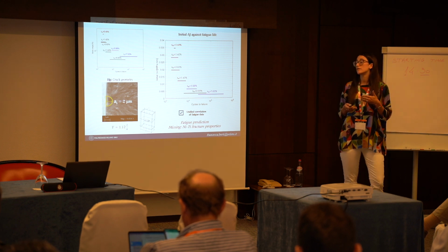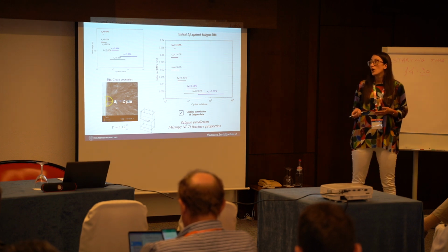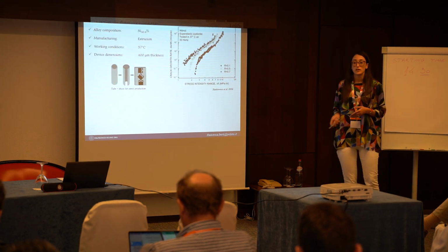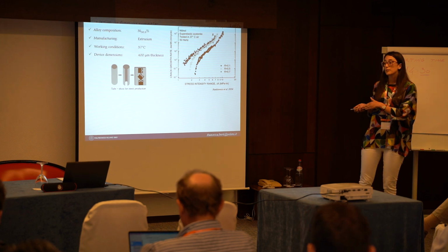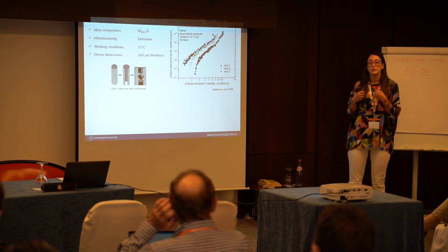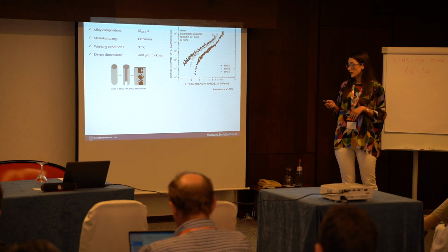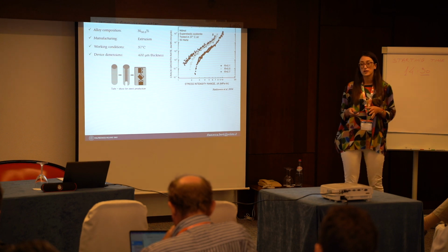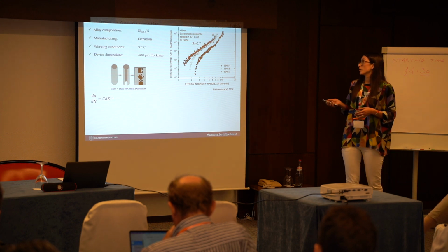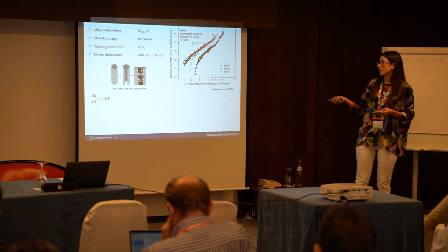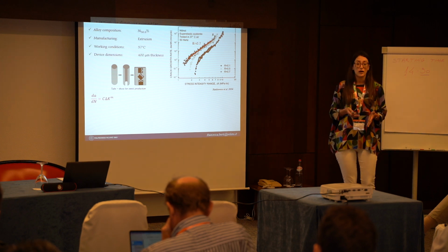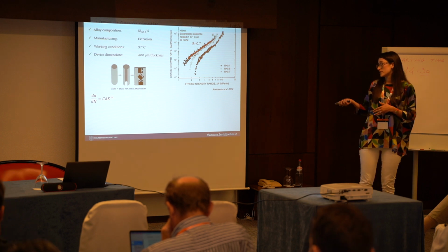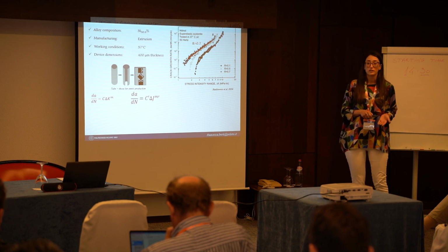And so we needed the fracture properties of this material. We were lucky: we went through the literature, and in these studies of Stankiewicz and colleagues, we found experiments involving samples obtained from tubes really similar to those used in stent production, and that is important. So we focused on the R ratio of 0.7, a condition close to that of the stents,